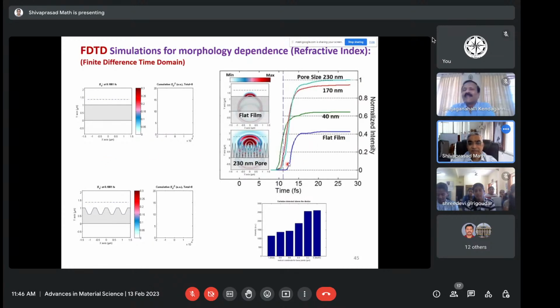The result is that you see a flat film based only on the refractive index. There's a big change in this material from a flat film to the porous film. So that means I can get more light out of those pores because of the shape of the films. I can see that also plotted in terms of this graph.